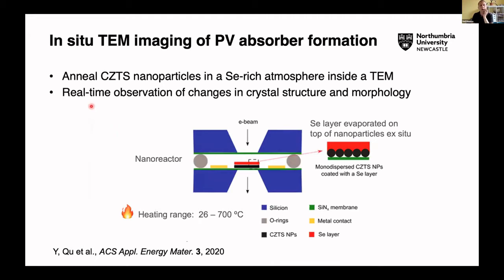So that was the manufacturing, what we're doing, and some of the applied stuff. This is a bit more about some of the physics, and this is an interesting experiment which we did in Singapore. The picture here shows what they call a nanoreactor. And inside the nanoreactor, we're able to put a single layer of our nanoparticles, then evaporate this red layer, a very thin layer of selenium, on top of that, and then inside the TEM, study the evolution of these nanoparticles in terms of crystal structure and morphology in real time over this temperature range, 26 to 700 degrees C. I think that was a very new experiment and really interesting and fun to do.